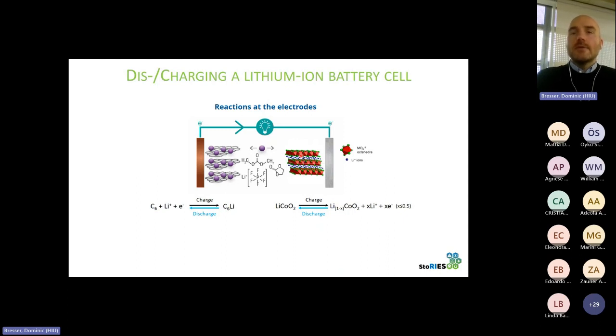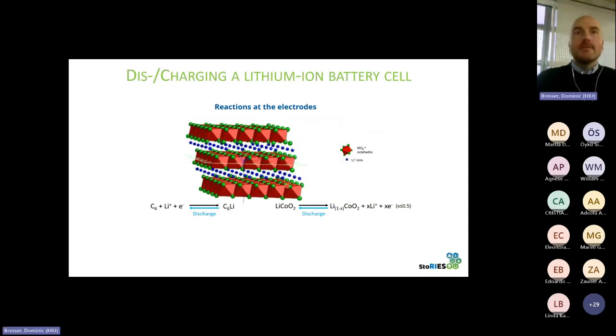So let's take another image for the crystal structure of lithium cobalt oxide. You see here the cobalt oxygen octahedra, as also apparent in the legend. And then you have the lithium cations in between these layers, and they can be reversibly intercalated and deintercalated. Very qualitatively speaking, you can imagine that if you remove all the lithium from this interlayer, then the structure might collapse. And apparently this collapse is irreversible, so that's what you want to avoid. Once again, a little bigger for those of you watching on the small screen.